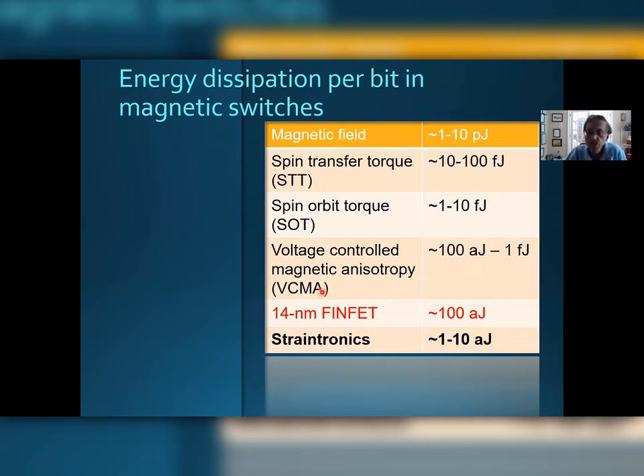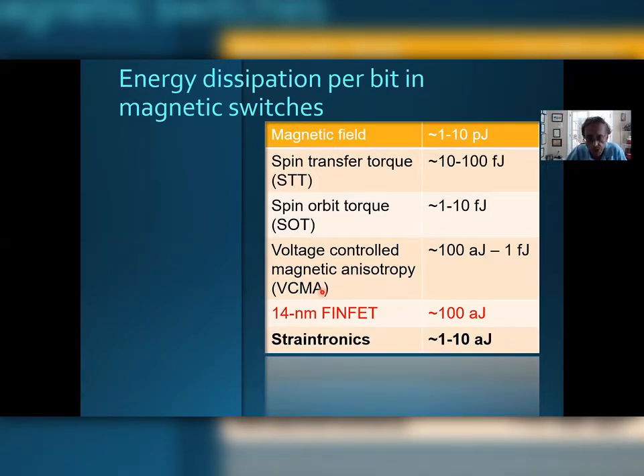How much energy is dissipated in a magnetic switch actually depends on how you switch it. The obvious way to switch it would be with a magnetic field, but it takes a lot of energy to generate a magnetic field on chip with a current, and the energy dissipation figures are typically 1 to 10 picojoules, which is huge. There are also more modern techniques that require passing a spin-polarized current to the magnet, such as spin-transfer torque and spin-orbit torque, and they are also fairly dissipative.